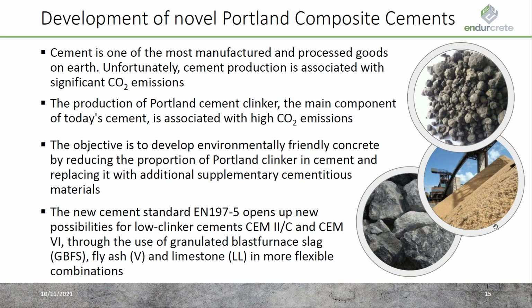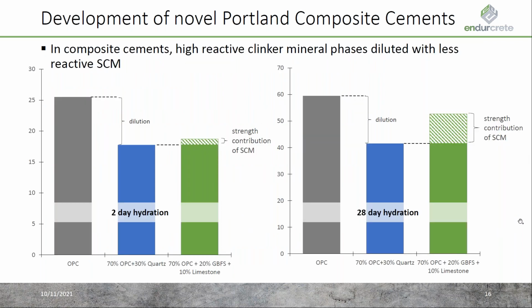And what is the problem when we lower the clinker content? It's the strength development in the cement. As you can see here on the left side, the 2-day strength of an OPC compared to a mixture where we replaced 30% of the OPC clinker by quartz, which is a non-reactive constituent. And because of the dilution of the clinker, we have much lower strength development.